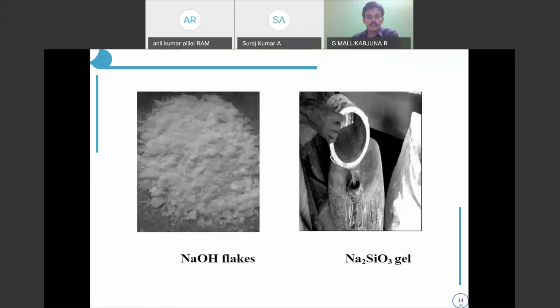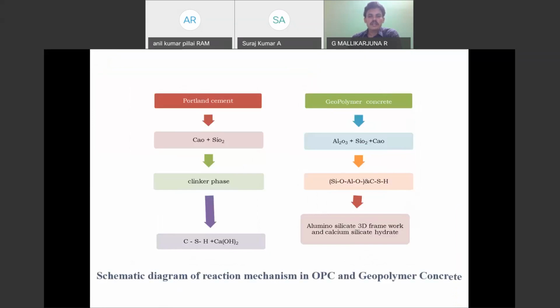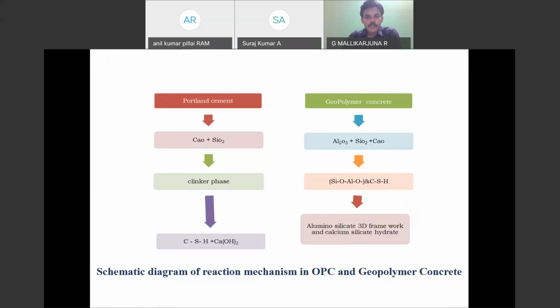And these are the NaOH flakes and the sodium silicate solution gel. And this is the schematic that we use to differentiate Portland cement and geopolymer. Here, calcium plus silica will play an important role. Coming to the geopolymer, we have alumina, silica, and calcium oxide. And coming to this, we have the clinker phase. But here, we have both the hydration process as well as the silicon, oxygen, aluminum process. And here we have an alumina 3D frame structure, and calcium silicate hydrate is also going to be formed whenever we go with this polymerization process.